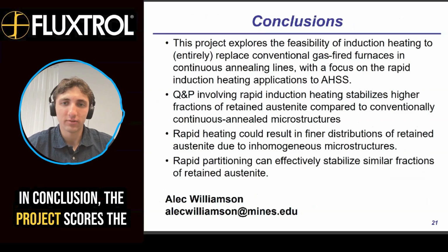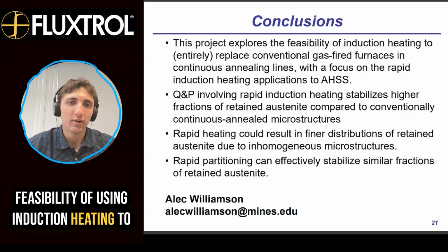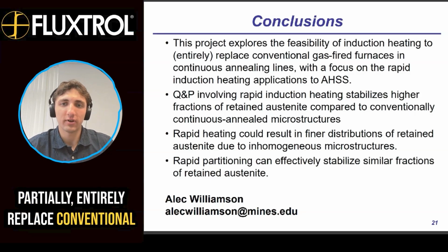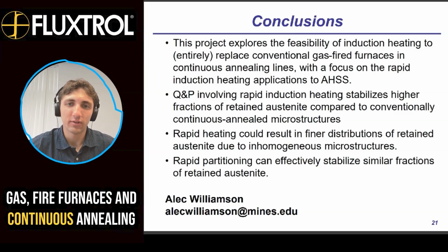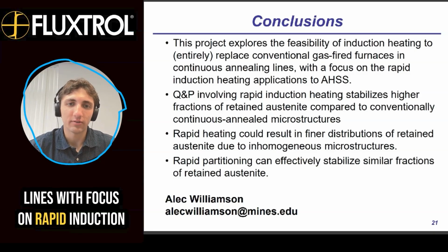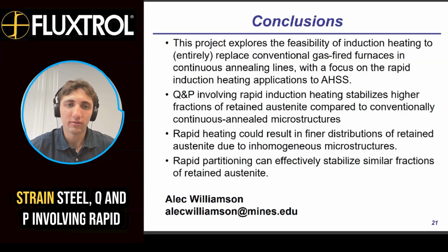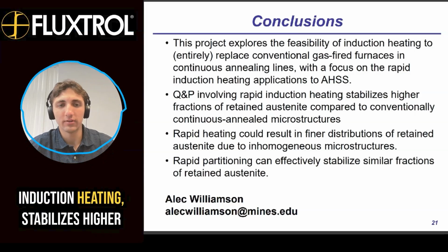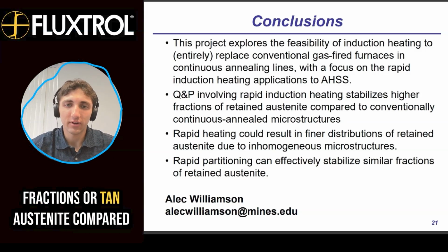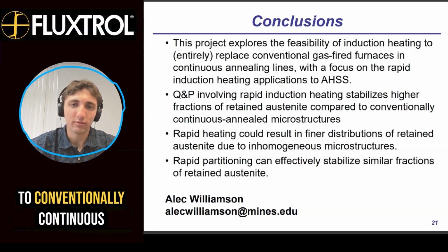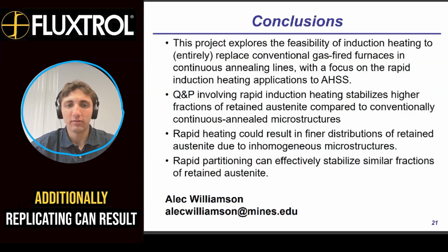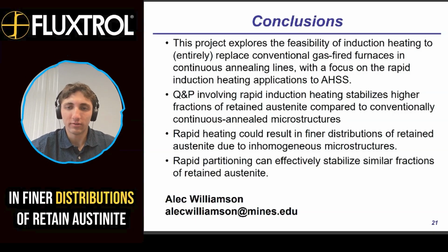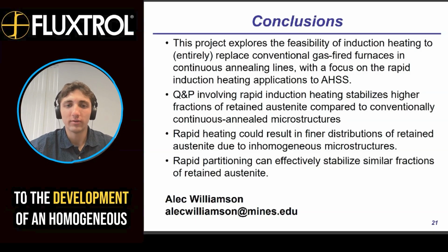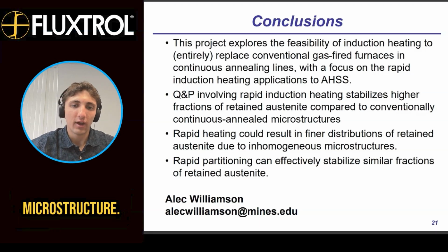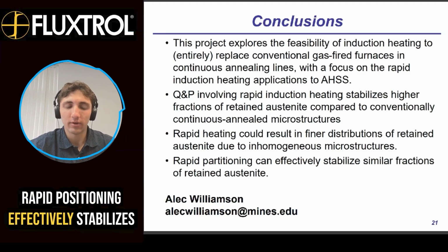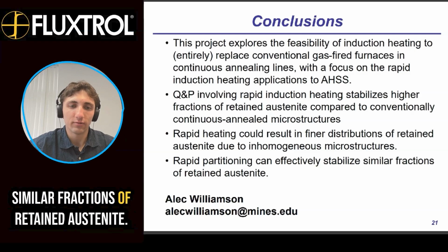In conclusion, the project explores the feasibility of using induction heating to partially or entirely replace conventional gas-fired furnaces in continuous annealing lines, with a focus on rapid induction heating applications to advance high-strength steel. Q&P involving rapid induction heating stabilizes higher fractions of retained austenite compared to conventionally continuous annealed microstructures. Additionally, rapid heating can result in finer distributions of retained austenite due to the development of inhomogeneous microstructure, and rapid partitioning effectively stabilizes similar fractions of retained austenite.